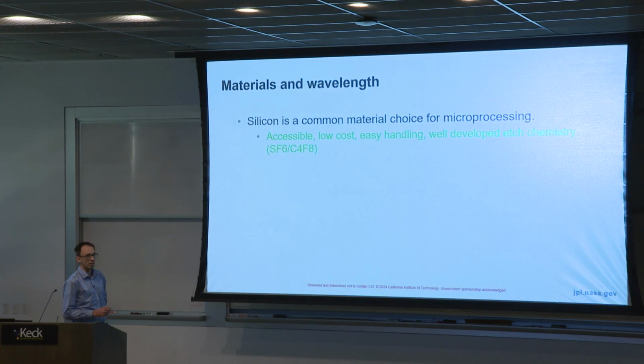It's very easy to get a hand on. The cost is fairly low. It handles really, really easily. So if you ever work with silicon, you know that it sits at this sweet spot where you're not constantly afraid of breaking the wafer. If you drop it a little bit, it doesn't necessarily break, but you can break it if you really want to. So if you need to cleave out pieces, that's not a big deal. And I think importantly for what we're talking about here, it has a very, very well-developed etch chemistry based on SF6 and C4F8, which is typically referred to as the or a Bosch process.